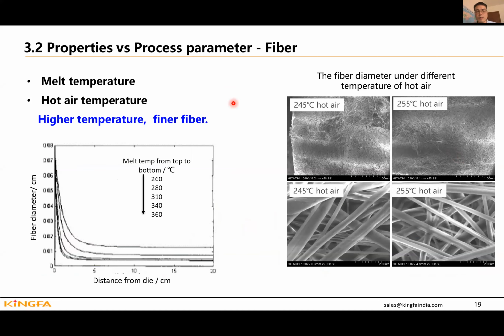Then second is about the fiber. The most important is the fiber diameter. We want to get a diameter of 2 to 5 micron. This is very critical to our filtration and to the strength. So first we check the temperature. Both the melt temperature and the hot air temperature can influence the fiber diameter. We first check this on the left figure. This is the distance from the spinneret to the collector.